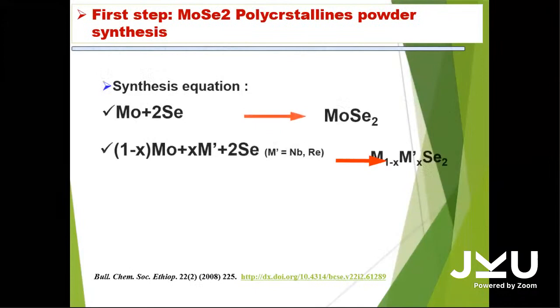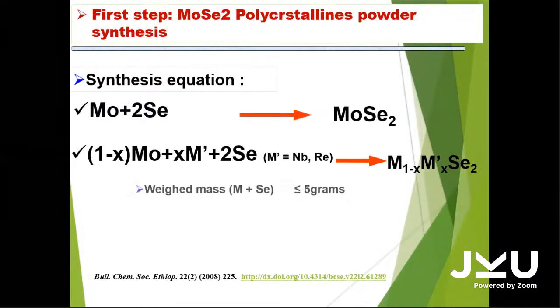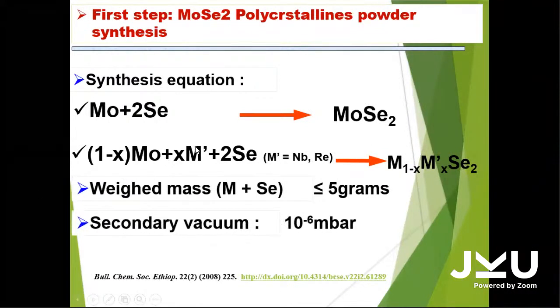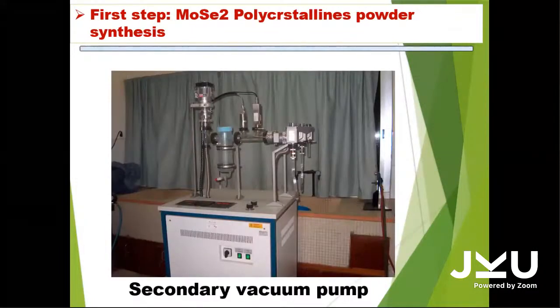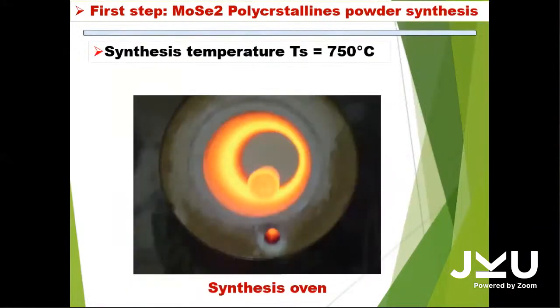To grow this material, we have two steps. The first step is the synthesis of the powder. For the synthesis of the powder, we weigh molybdenum and selenium in stoichiometric proportions and put them in a tube. Then the tubes are connected to a vacuum pump, in which we make a high vacuum to avoid oxygen oxidation. After this step, the tubes are closed using a torch and placed in an oven where the temperature is increased to 750 degrees for 1 day, and we maintain this temperature for 5 days. Then the product formed is allowed to cool down for 24 hours.